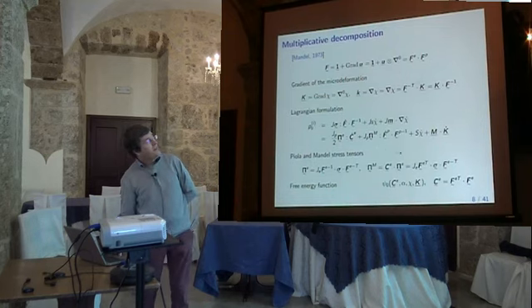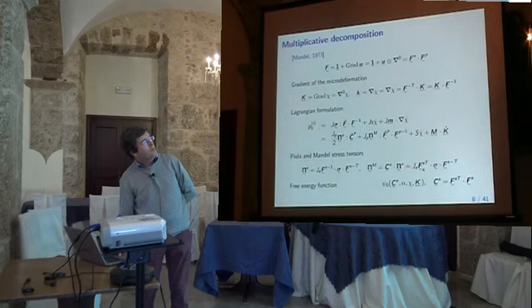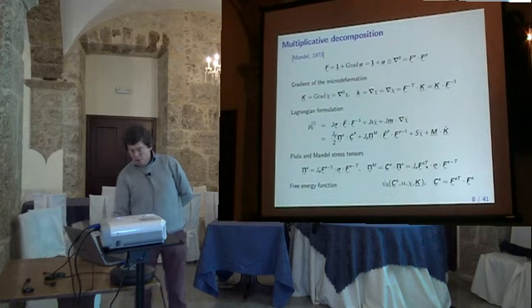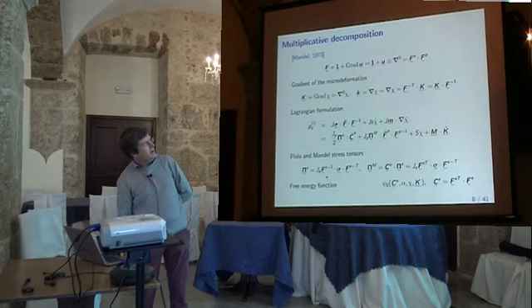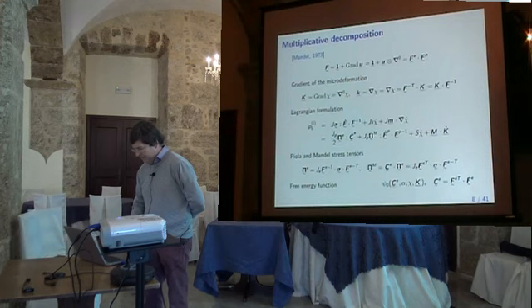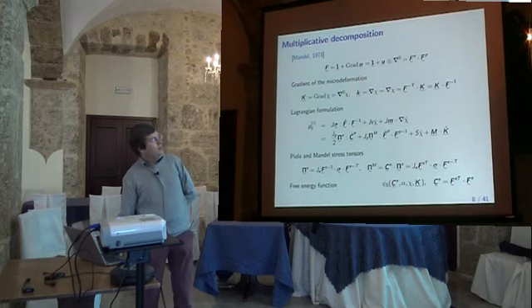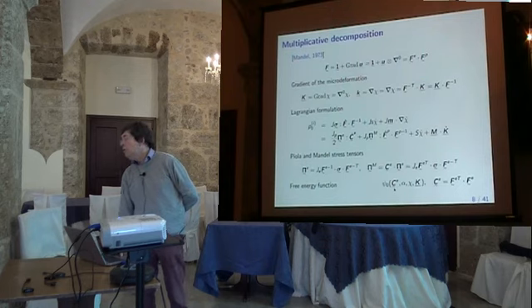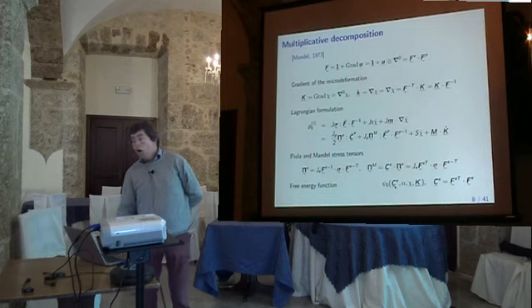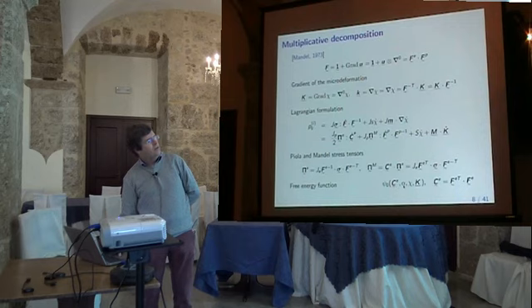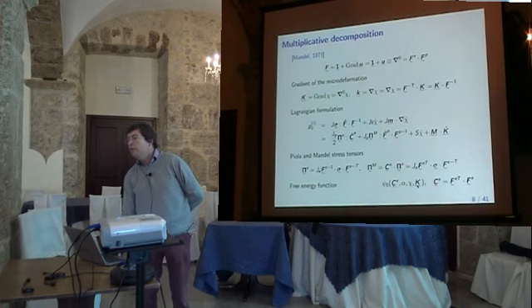And the difference is the variance here. You see, the transport by the elastic deformation is by the transpose here to go back to the intermediate configuration, release configuration, whereas for Piola, by the inverse of the tensor. So this is a difference, okay? So these are the quantities we have now, and we put all this into the free energy density function. So we have the elastic strain. We take the left Cauchy-Green tensor on the intermediate configuration, so purely elastic release. And we have some internal variables if you want some hardening. Of course, we will need that. And we have this micro deformation and its Lagrangian gradient. So this is the framework we have.